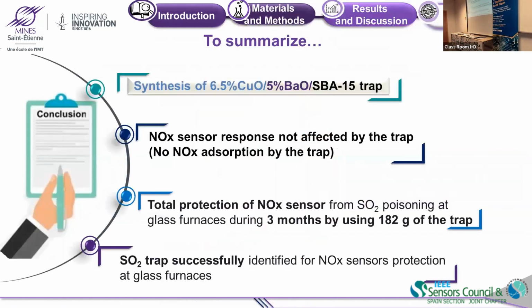To summarize, we synthesized the trap with a proportion that gives a NOx sensor response that is not affected by the trap. There is no NOx adsorption in the trap. And we can get a total protection of the NOx sensor for 3 months with less than 200 grams. So we have a successful trap developed for this application.